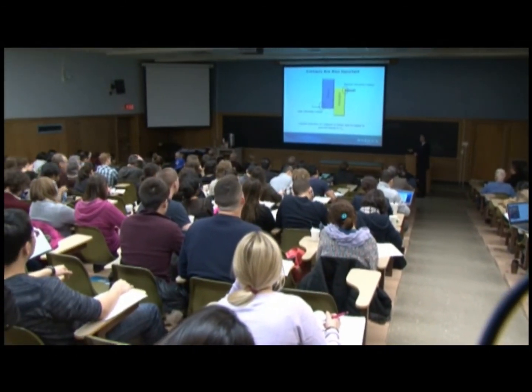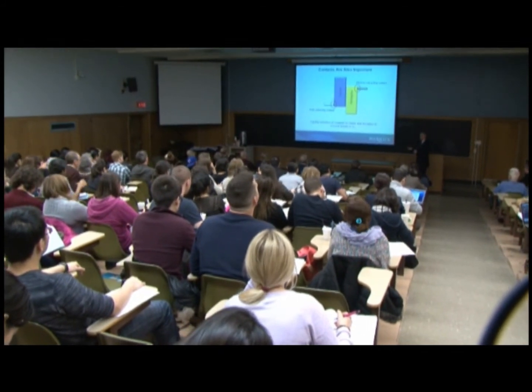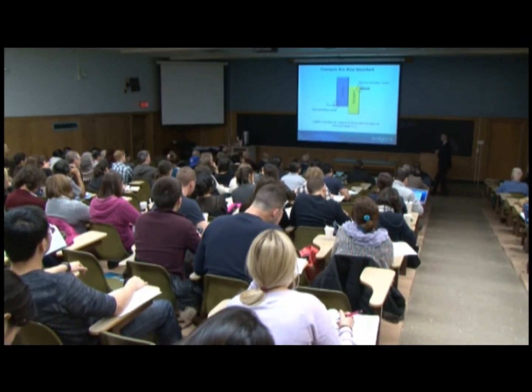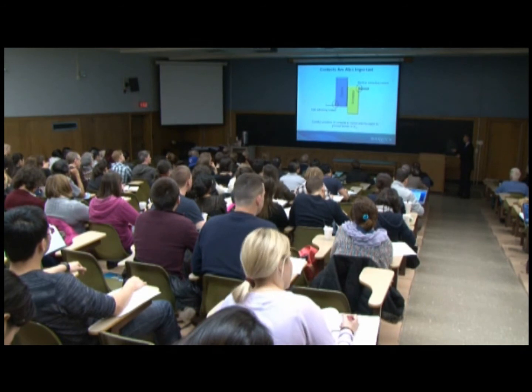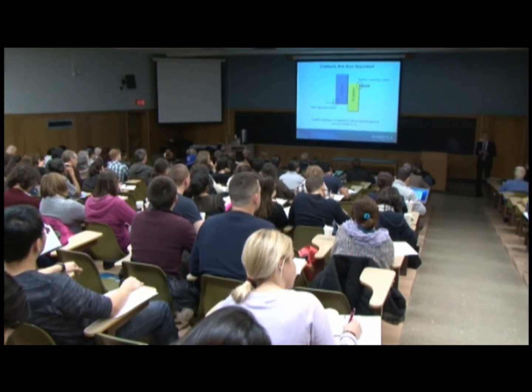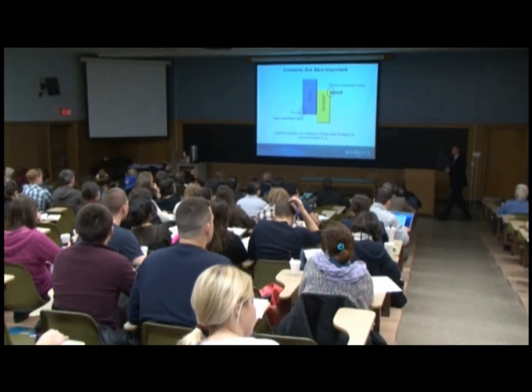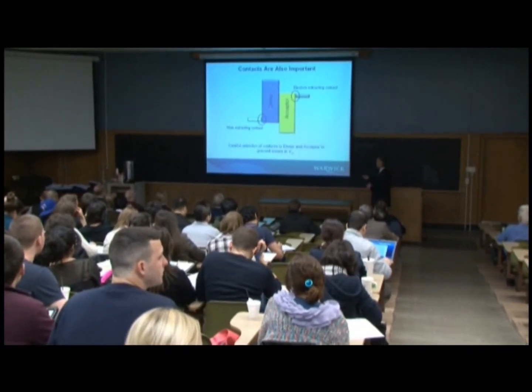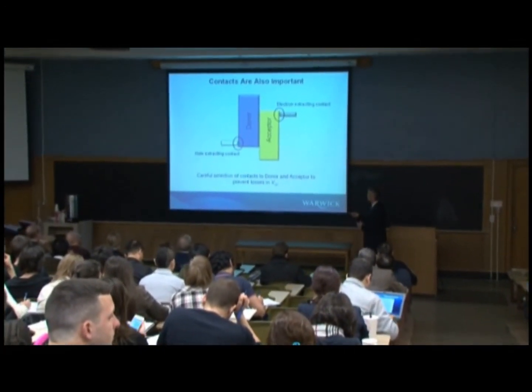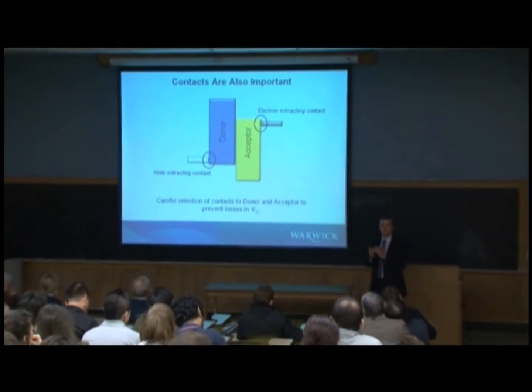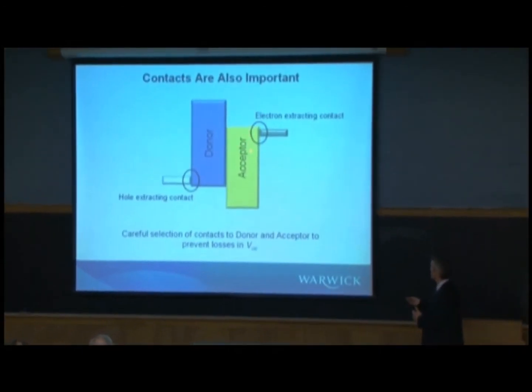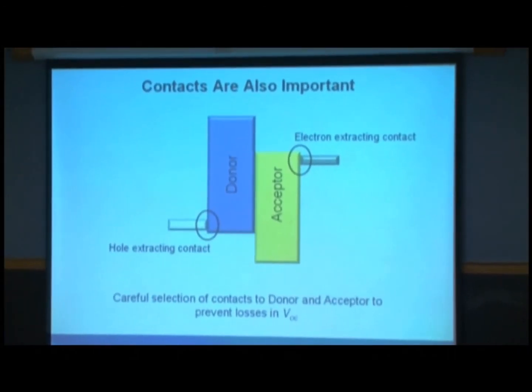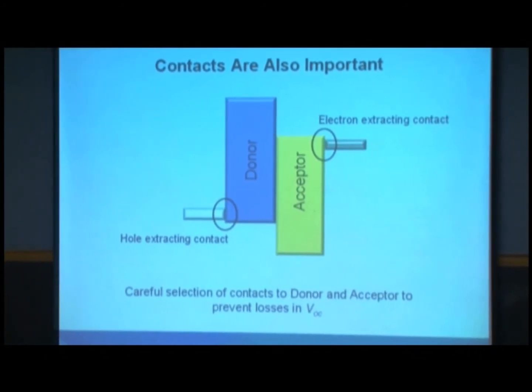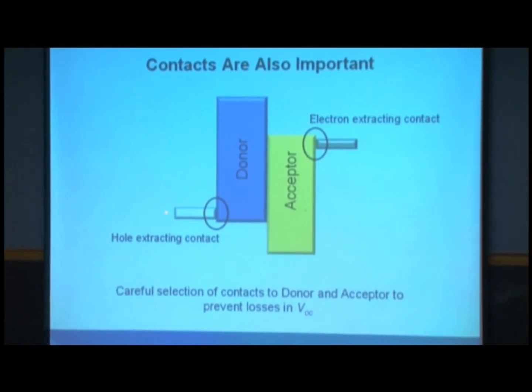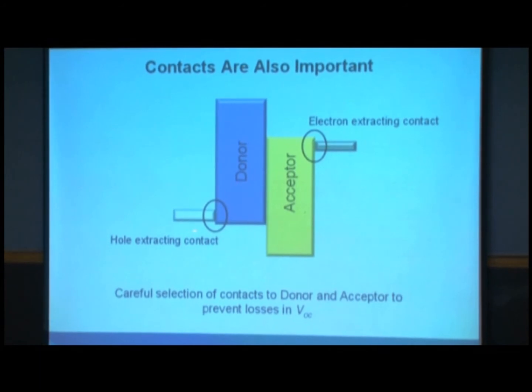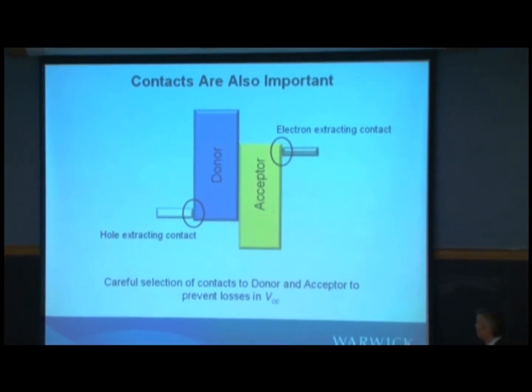Okay, so I want to talk a bit about the electrodes. I've talked essentially about this interface, which is very important for device behavior, but the interfaces with the electrodes are also very important. You've got 2 electrode organic interfaces. You've got the interface between the donor and the transparent conducting electrode, which is typically indium tin oxide, and the interface between the acceptor and the metal, which is typically aluminium. Now I'm going to concentrate on this interface. It's the one we've done the most work on, the ITO donor interface.